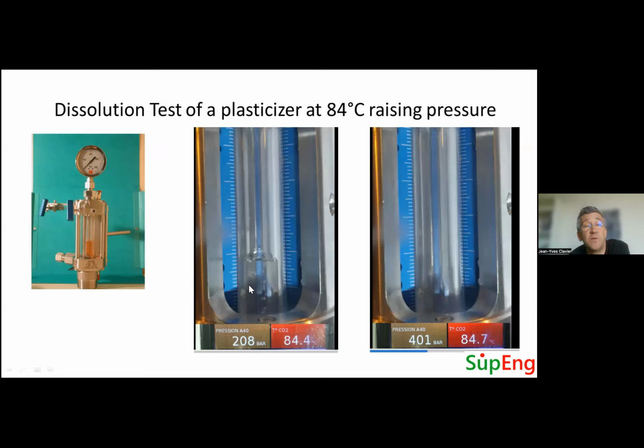For solubility measurements, for instance, we use this kind of sapphire cell system. You see one example here. We place the pure extract in the cells. We have a little flow of CO2 that we try to saturate, optimizing the contact. And what is going out allows us to determine the solubility of the extract in CO2. And the good point about this technology is that we can play easily with temperature and pressure.